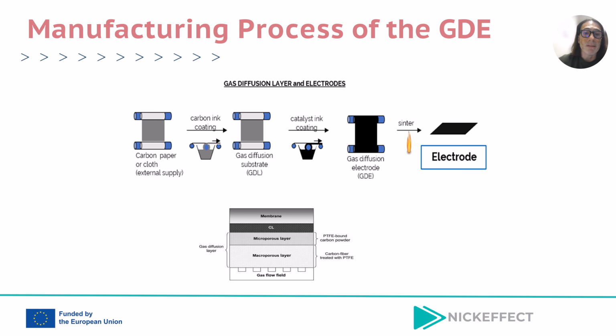Finally, the finished GDE undergoes rigorous quality control. We test for things like pore size distribution, electrical conductivity, catalytic activity. This ensures every electrode meets our standards for performance and reliability. In the slide below, you can also see the internal structure of the GDE. The membrane in the center, a microporous layer, and a PTFE-bound carbon particle layer which enhances gas diffusion and water management.